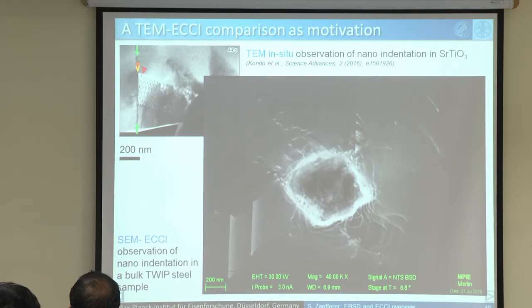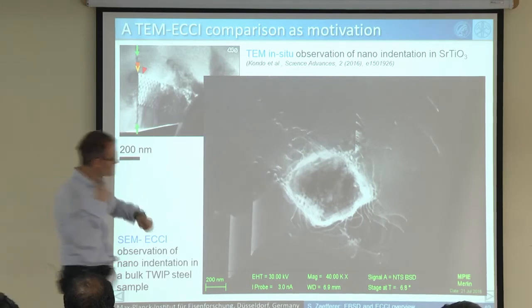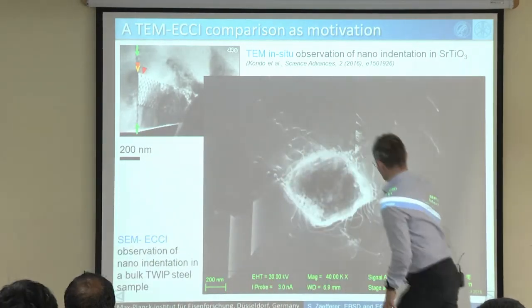So you indent into a bulk sample. You don't take a thin foil. You just take a nicely prepared sample. You indent. This was a 50 nanometer deep indentation, and then you look on all the dislocations which have formed when you do 50 nanometer indentation. Then you can make an indent here next to it, 100 nanometer indentation or 25 nanometer more. You can do all these kinds of experiments a little bit ex situ, but nevertheless, you can see very beautifully in a SEM all the dislocation structures forming here.